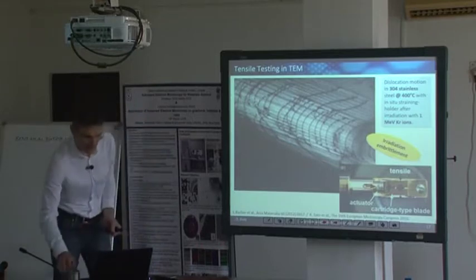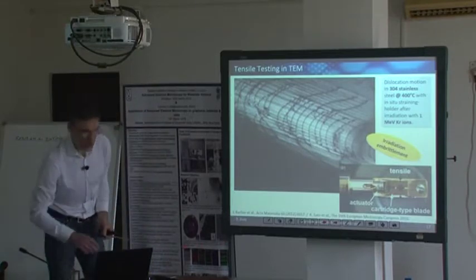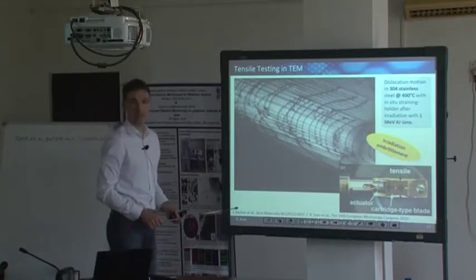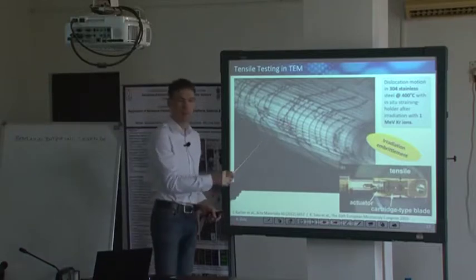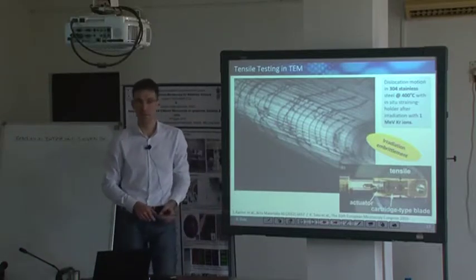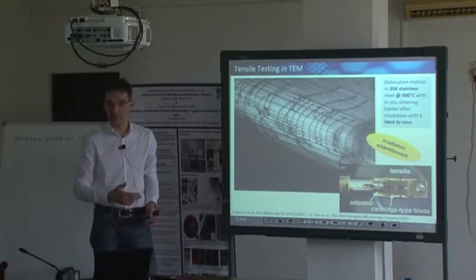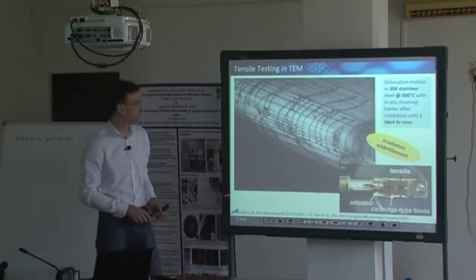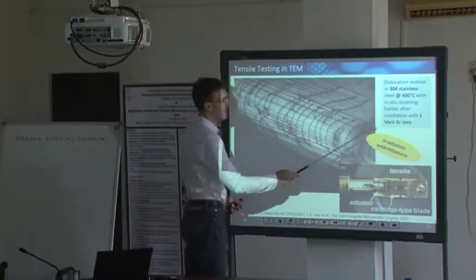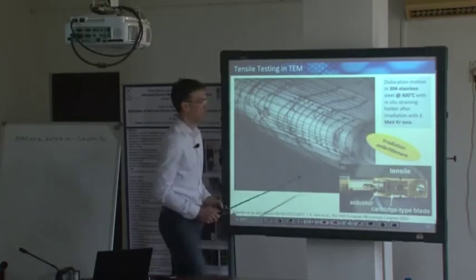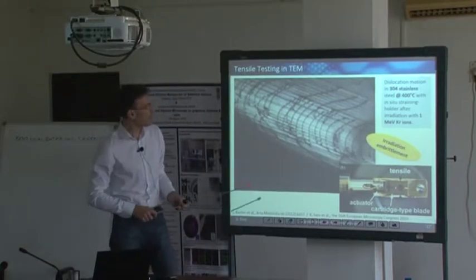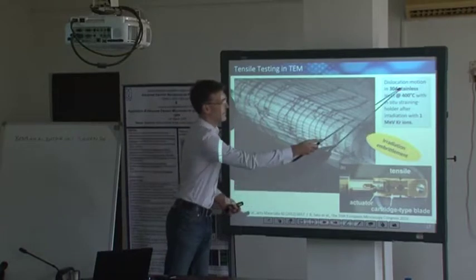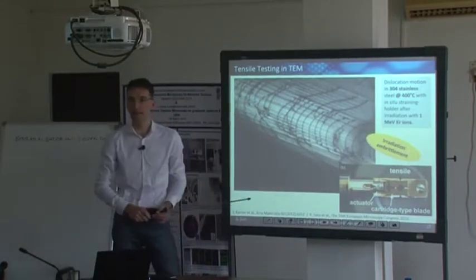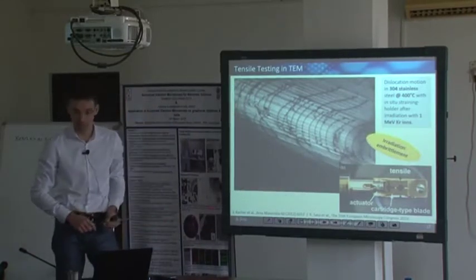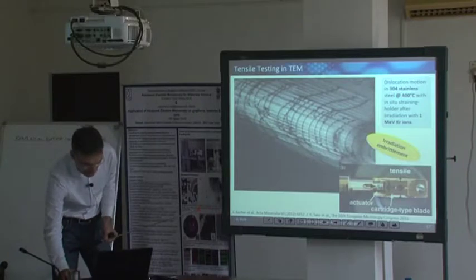And here on the left-hand side, there's a video where people demonstrated the movement of dislocations. Dislocation movement in principle is pretty fast, of the order of the speed of sound in matter, which would hardly be observable. This is a special material that was irradiated. This is an irradiated stainless steel, and that caused some hardening. So the movement of dislocations is strongly limited.